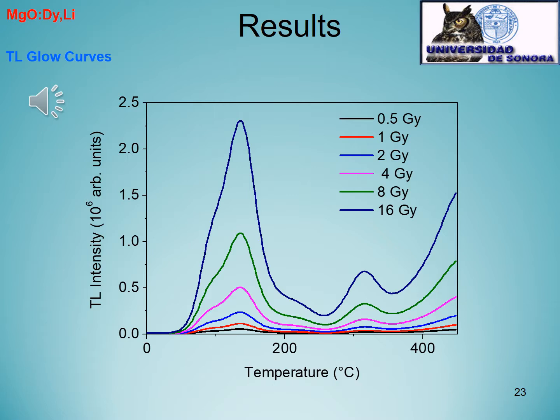Also, as the dose increases, the intensity increases, but the peaks remain in the same positions, which is an indication of first order kinetics for the TL processes, as we observed for other materials shown in this presentation before.